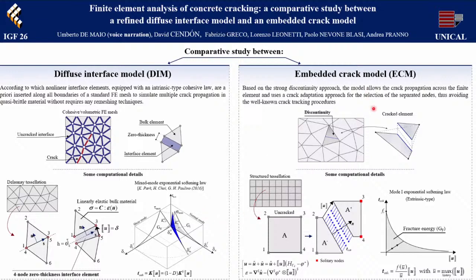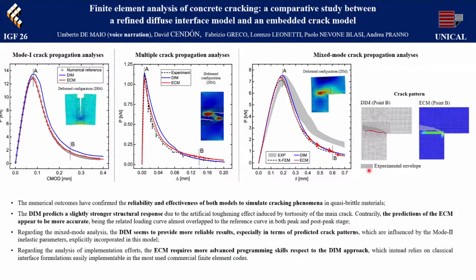On the other hand, an embedded crack model combines the well-known strong discontinuity approach, able to introduce a displacement jump in the finite element kinematics once a certain stress criterion is satisfied, and a cohesive zone model to simulate the cracking behavior along the discontinuity. These two models have been compared by analyzing the cracking behavior in concrete specimens subject to both mode 1 and mixed mode fracture and multiple crack propagation.